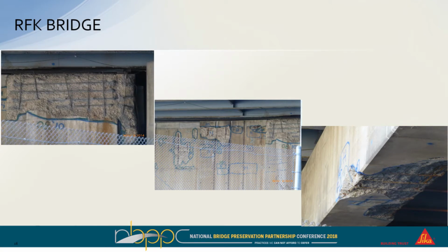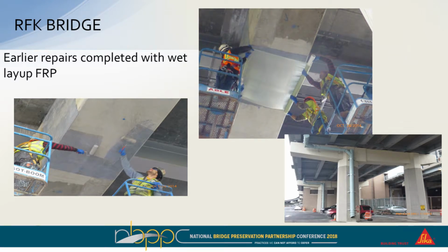This complex opened back in 1936, so it's been around for over 80 years now, and there's been quite a bit of concrete deterioration, a lot of de-icing salts, corrosion damage that has taken place. So the purpose here was to do a lot of concrete repair and patching, and then also provide a FRP glass system for confinement. They didn't want to have to come back and work on these patches again in the future. So this was not necessarily a strengthening application, but really more a confinement for the patches.